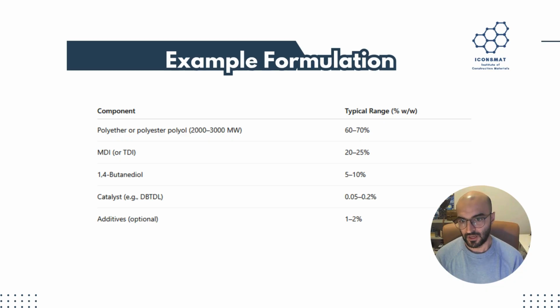And then we have butanediol, if I'm pronouncing it right. So what the third item does is that it creates chain between MDI and polyether or polyester. You need a catalyst and also additives as well. So one of the additives that I think I'm going to be using later on is a degassing component to limit the amount of CO2 gas generated because it's just no good for the tensile test. And these are the typical mix ratios that you may need to have a good flexible polyurethane sample with an acceptable tensile strength.